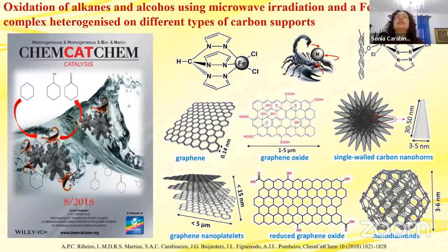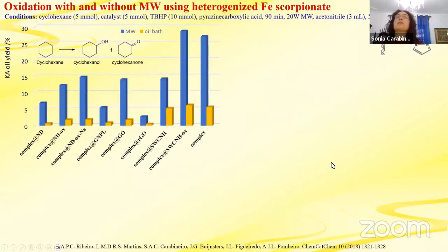We also tested the oxidation of alkanes and alcohols using microwave, and this same iron scorpionate complex heterogenized on different carbon supports. And this was a cover of this number of ChemCatChem journal. And we have here the carbon materials that were used to heterogenize this complex. It was graphene oxide, single-walled carbon nanohorns, graphene nanoplatelets, reduced graphene oxide, and nanodiamonds. So a lot of carbon materials.